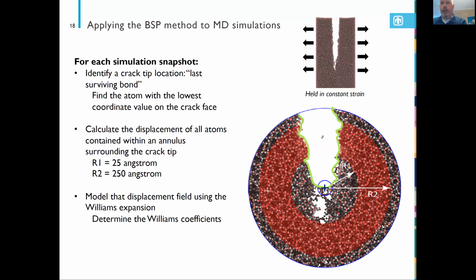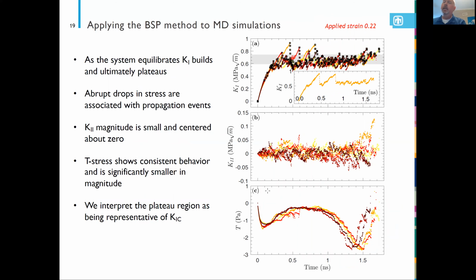And that's what I'm showing here. The top figure is showing the K1 stress, the middle figure is the K2 stress, and the bottom pane is the T stress. This is in time, and I note that the fracture sample will completely break in about, I think this is where it completely broke, 1.75 nanoseconds. Again, extremely fast times on MD length scales.